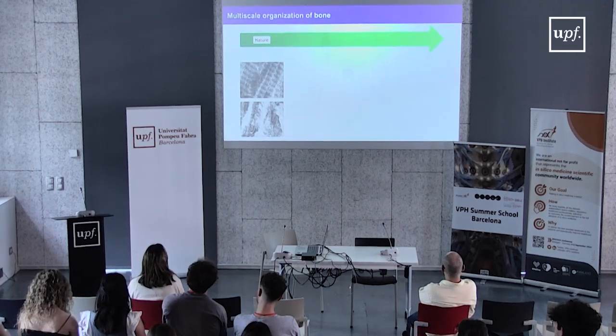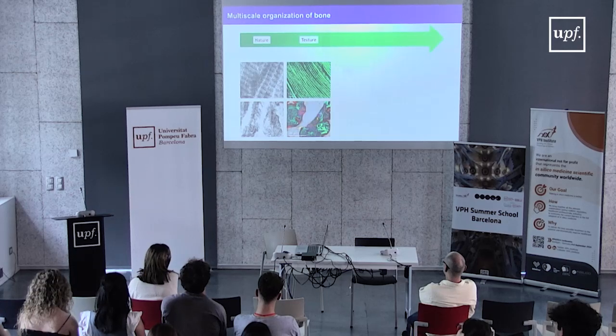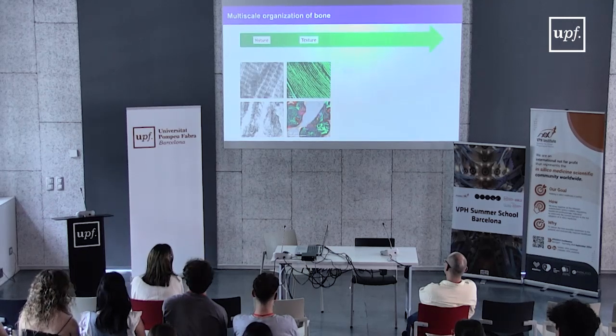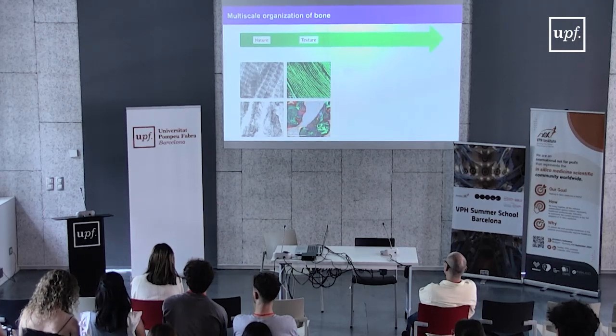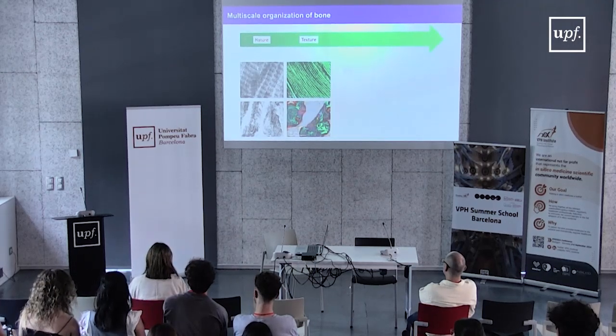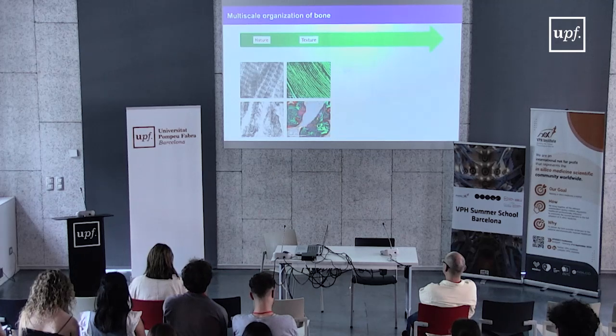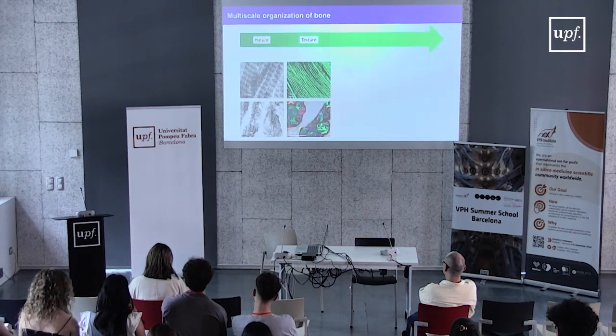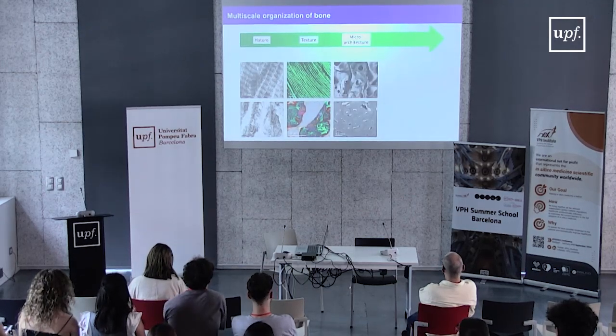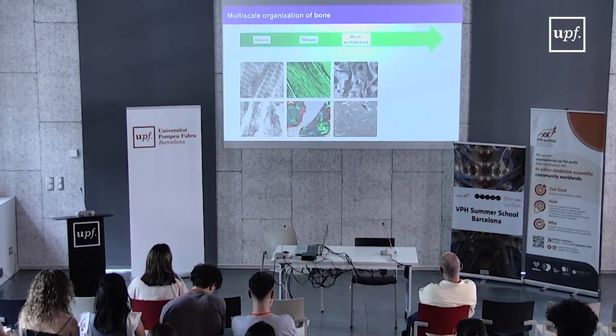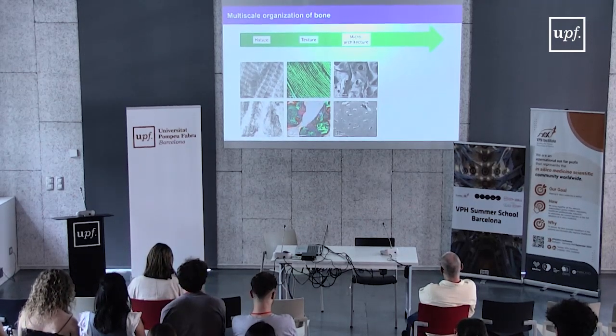Now, the collagen and the mineral will compact and will form what we call the texture of the bone. So both will compact to form lamella. You have on the top in here lamellar bone. And this lamellar structure is important also to resist to fracture. In pathological situation, you can have another organization of the texture, which is called woven bone or non-lamellar. And you can see in here by polarization that we don't find this pattern of dark and bright line in the bone.